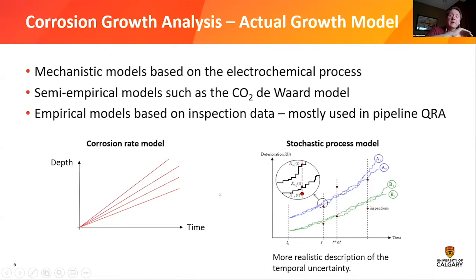On the left, where we always assume a straight line with an uncertain slope, does not represent the proper corrosion growth. Although they're preferred in industry, They're relatively simple in terms of the mathematical handling. From a probabilistic, uncertainty perspective, they do not capture properly the temporal uncertainty in the corrosion growth. So our focus when it comes to actual application should be the application of stochastic process models to model the actual corrosion growth over time. So the actual corrosion growth over time, that is one major uncertainty when it comes to predicting the future defect size.